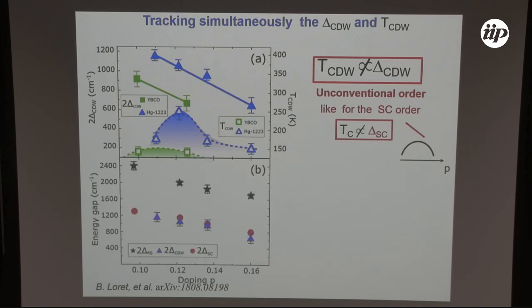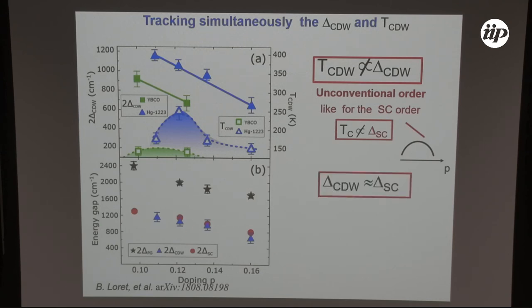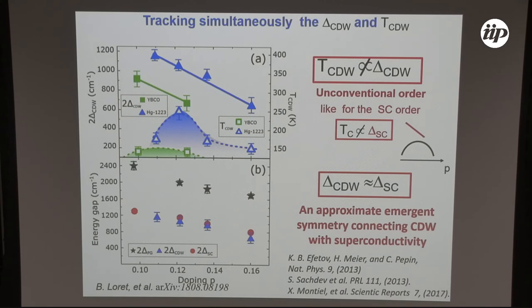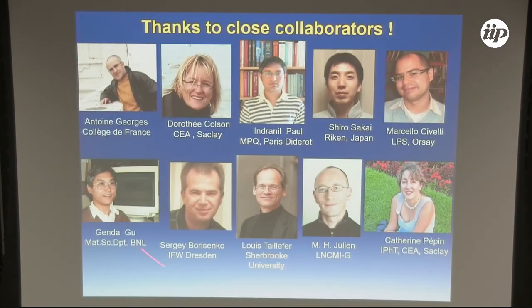We can now plot together the energy of the pseudogap (black stars), the superconducting gap (red dots), and the charge density wave energy (blue triangles). What is surprising is that the energy of the charge density wave is very close to the energy of the superconducting gap. This relation suggests there is probably an approximate emergent symmetry connecting the charge density wave with superconductivity. I invite you to look at the theory corresponding to this proposal of emergent symmetry, and I thank all my close collaborators on this subject.